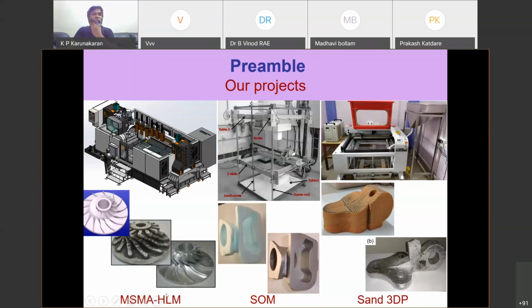Subsequently, we realized that we can also hybridize a few more things. For example, when we try to create a layer, the outside of the layer only needs to be more precise geometrically. So we used laser deposition in 5-axis mode to create the outer periphery of the boundary of the layer. And then we fill the inside with rasters using 3-axis in MIG, metal inert gas cladding. So this way we were able to combine different energy sources, laser and MIG.